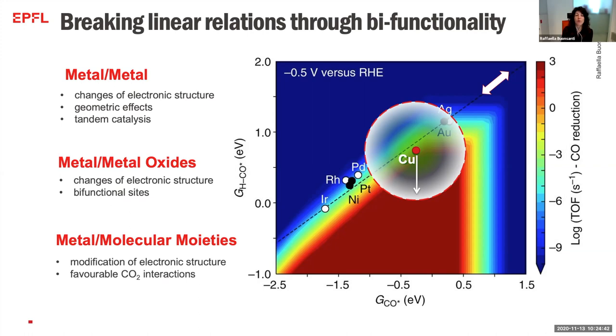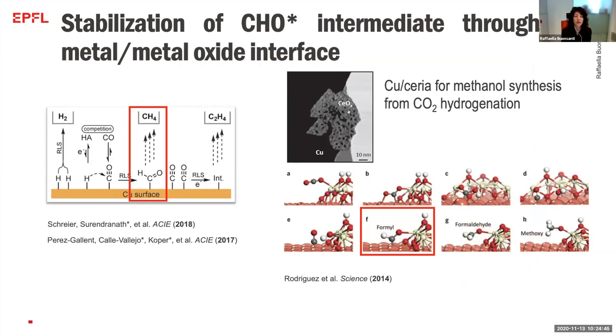So the first work that I will share with you is the work of my student Denaz. Here, what I mentioned before is that this CHO intermediate is crucial to form CH4. So if we want to promote the electrochemical CO2 reduction and the production of CH4 instead of hydrogen, we would like to stabilize this intermediate. If we take inspiration from CO2 hydrogenation, actually in CO2 hydrogenation, a similar intermediate forms and is stabilized by creating interfaces between ceria and copper metals.